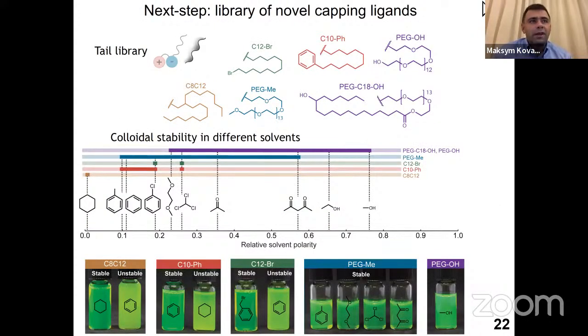With this knowledge, we have tested the whole library of ligands. So we kept the primary ammonium-based zwitterionic phospholipid group, and we engineered a lot of different organic residues. And this is the first time that you can have perovskite nanocrystals dispersible in basically every solvent that you may come up with, except water, because in water the material itself dissolves, the perovskite material. But now you can disperse perovskite nanocrystals in alcohols, in acetone, or in very apolar solvents. And you simply accomplish that by the group which you bind to your phospholipid.